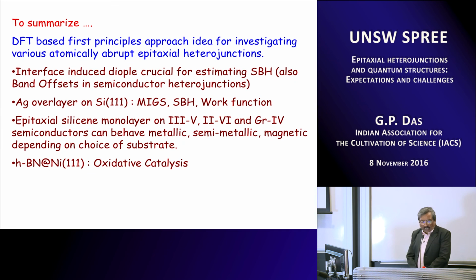So we started with the Schottky barrier height example, and the role of the interface induced dipole, which is crucial for estimating the Schottky barrier height. In fact, I did not discuss that, but not only the Schottky barrier height, but also the band offset in semiconductor heterojunctions is crucially dictated by the interface. Then I came to another example, namely silver overlayer on silicon 111, where the metal induced gap states, the work function, etc. are found to be in very nice agreement with the experimental results. The epitaxial silicene monolayer on the 3-5 and 2-6 semiconductors can behave metallic or semi-metallic or even magnetic depending on the choice of the substrate.